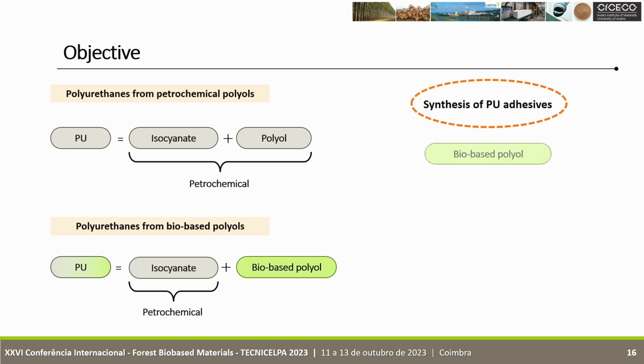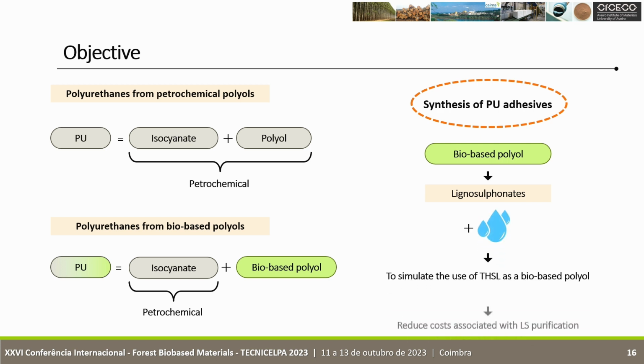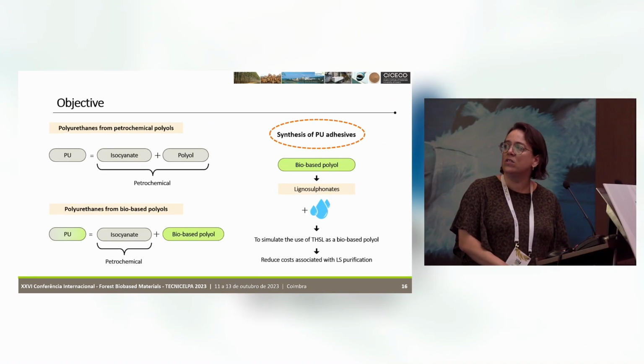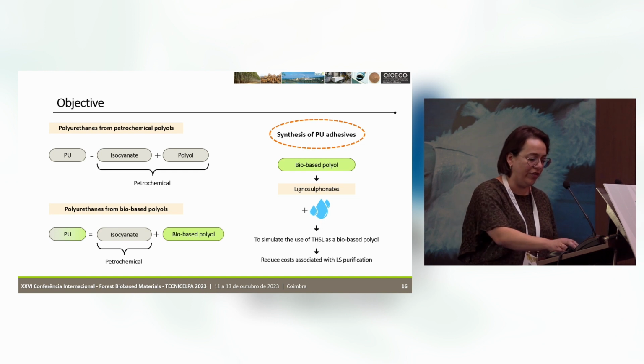In this case, polyurethanes were made where lignosulfonates were the bio-based polyols. The particularity of this formulation was to add a little bit of water to simulate the use of thick sulfite spent liquor, because the final goal would be to use the liquor instead of the purified lignosulfonate, to reduce costs related to lignosulfonate purification.